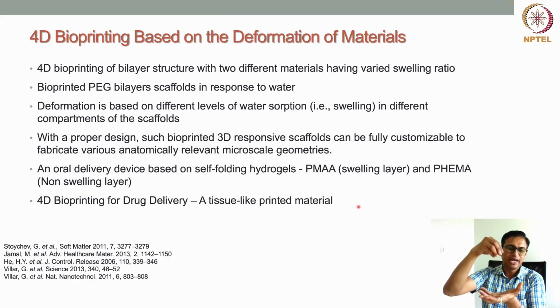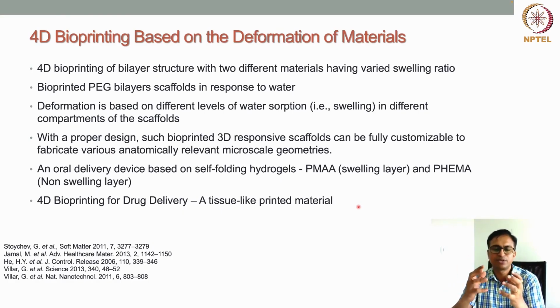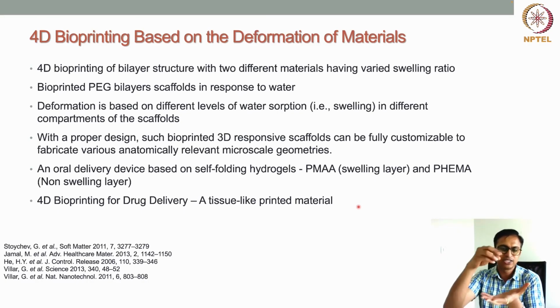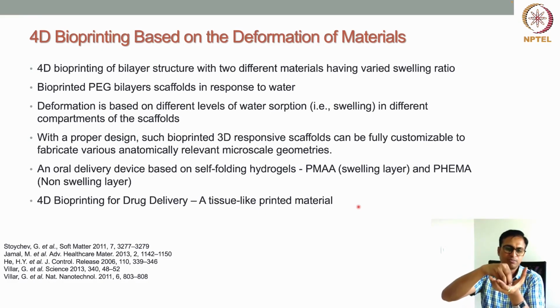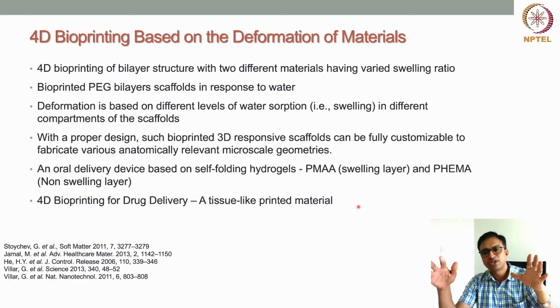oil drop. What will happen is, as soon as the water droplet comes out of the nozzle, and it is in the environment of oil, the surfactant particles will coat the water droplet, right, and then it will get deposited within this oil drop. Similarly, when the next water droplet comes, that will also get coated with the surfactant, and that will also sit within the oil drop. So all these printed water droplets within this big oil drop will be discrete, but they will get connected to each other.